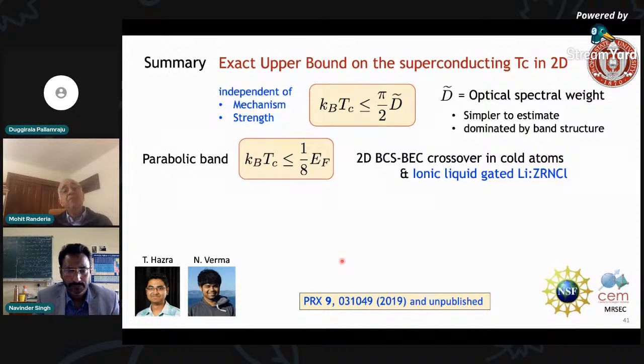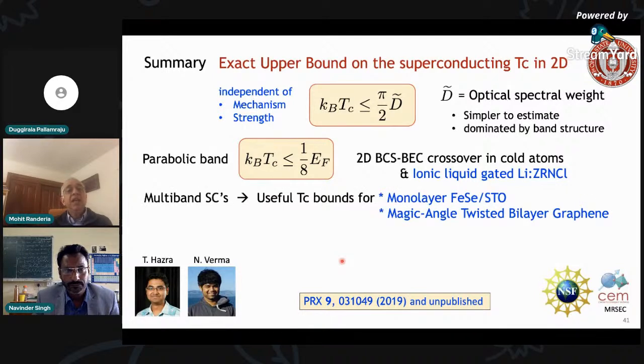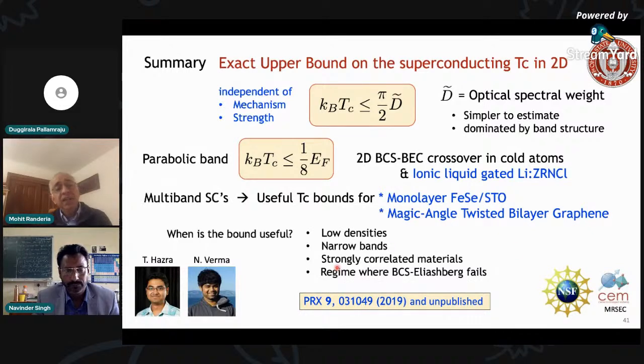And this, I believe, can be seen in the BCS-BEC crossover in cold atoms and has been seen in the BCS-BEC crossover in this ionic liquid gated material. It's a remarkable experiment. Okay, and for multi-band superconductors, where we do not have such a simple expression, the bound still holds, and we have very useful TC bounds for systems where superconductivity is totally ill understood: monolayer iron selenide and magic angle twisted bilayer graphene. And what we have learned is that these bounds are useful precisely where conventional BCS theory is not good: low densities, narrow bands, and strong correlations. So with that, thank you very much for your attention, and I'm very happy to take questions.